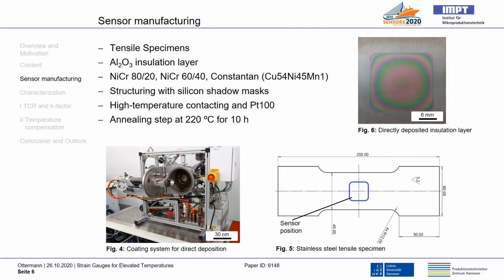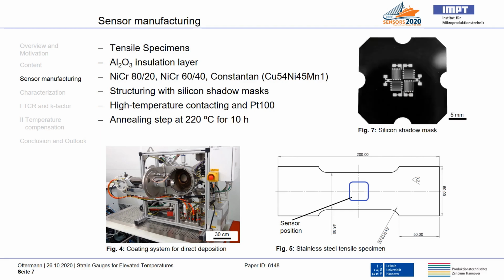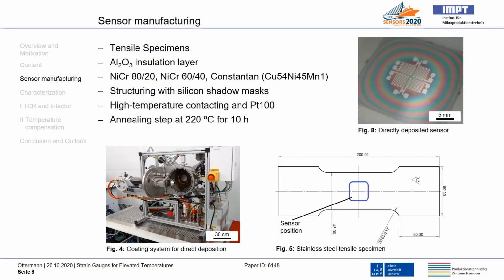The deposition starts with an alumina insulation layer, which is necessary due to the metallic substrate. Afterwards, the sensor layer is deposited. The structuring happens by the usage of silicon shadow masks, as shown in Figure 7. Different sensor materials are investigated in order to find the best material for our application. These materials are nickel chromium 8020, nickel chromium 6040, and constantan. The result is a directly deposited sensor as shown in Figure 8.